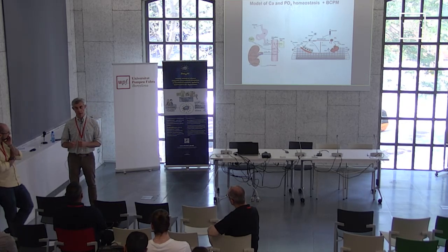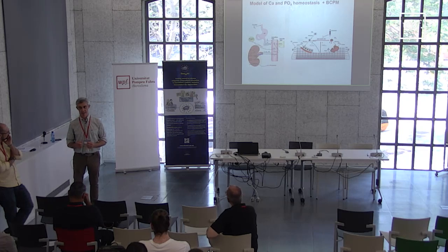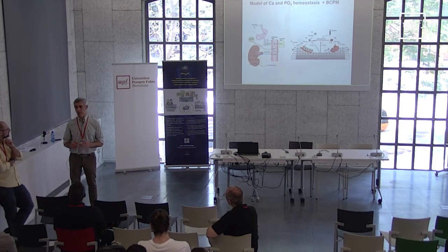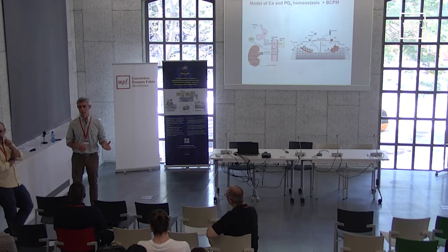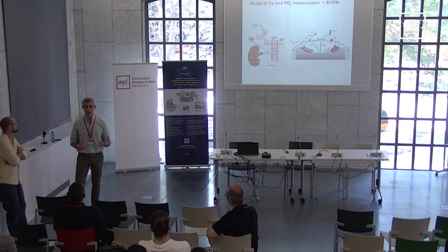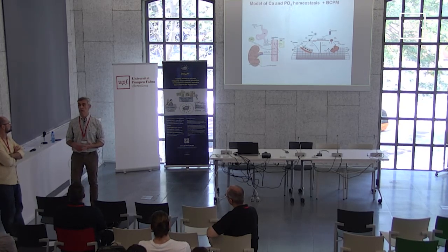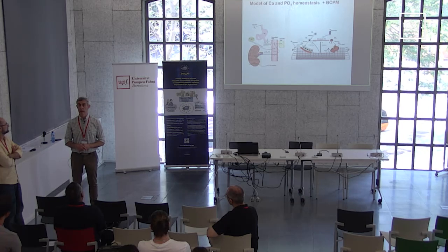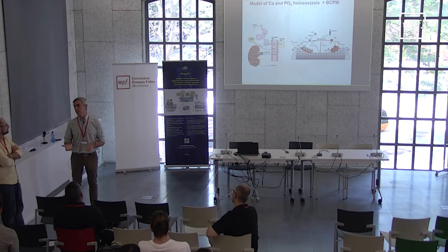Good, but complex question. It's a good question, but very complex, because we still don't know much about which are the most influential mechanisms on bone fracture. We guess that in trabecular bone, for example, the quality of trabecular microstructure can play a key role. And in the case of cortical bone, I would say that mineral content is the key, because the variation of porosity in cortical bone is not that significant.